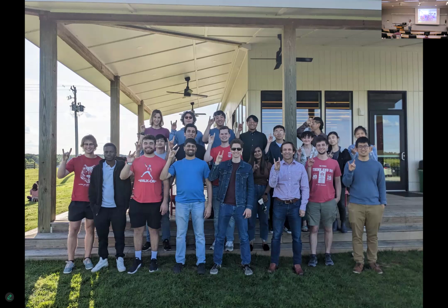So the metal that we print, first of all, you can print pure gallium. You just melt it and print it, no problem. And then that forms, of course, gallium oxide. With the alloy that we print, eutectic gallium indium, it's about 25% indium. And it turns out it's actually a little bit complicated. So if you go into a vacuum environment where there's no oxygen and you remove the oxide, indium actually goes to the surface because it has a lower surface energy. So indium prefers to be at the surface.